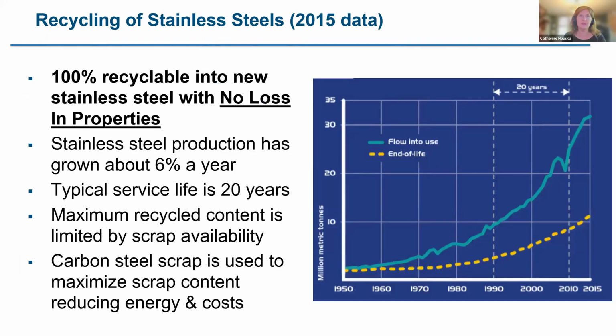First, I want to point out that stainless steel is 100% recyclable into new stainless steel. There is no loss of properties. And we use as much recycled content as we possibly can in stainless steel. Because stainless steel production has grown at about 6% a year, as you can see in this graphic, and the typical service life, when you look at all applications, is about 20 years, you can see there's a significant gap between the growth and the scrap that's going to be available. So that maximum recycled content is limited by scrap availability. So we do use carbon steel scrap to increase the total scrap content in stainless steel, because we want to maximize it. It reduces energy use and costs, and of course, reduces the carbon footprint.